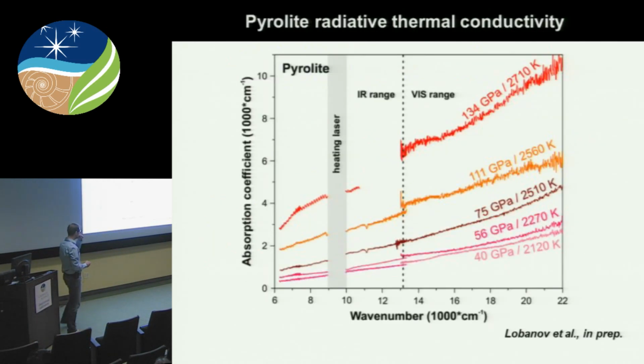We can do similar measurements in the visible range. And these are completely different experimental setups, and we have to stitch the spectra together later on. But they do agree that the high temperature sample is a lot more absorbing than it is at room temperature. So in here I'm showing you just absorption coefficients of pyrolite as a function of pressure and temperature.